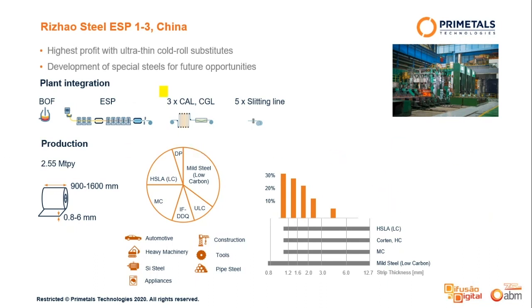You can see here after ESP are following the annealing and the galvanizing lines. Saving the investment for cold rolling lines and related operation costs and selling direct application, this is the motto of Rizhao Steel. Even though the plant is capable of producing up to 12 millimeters, the focus is completely on ultra-thin gauges. You see here in this diagram, the possibility is from 0.8 to 12.7 millimeter, but they are mainly producing below 3 millimeter thickness.